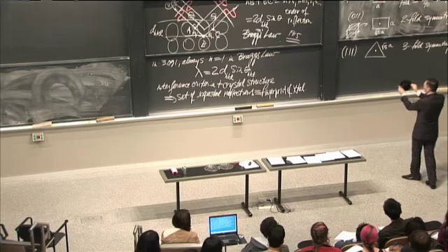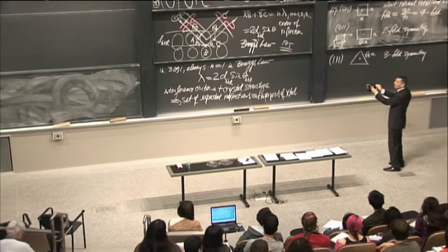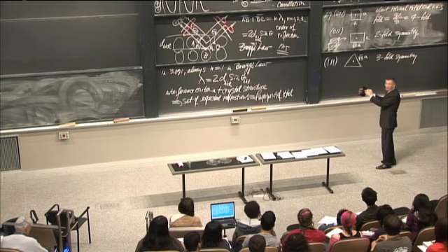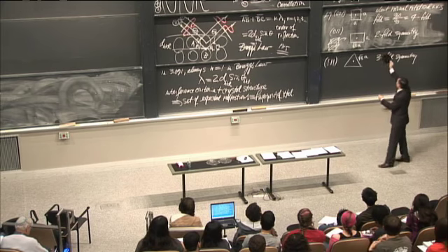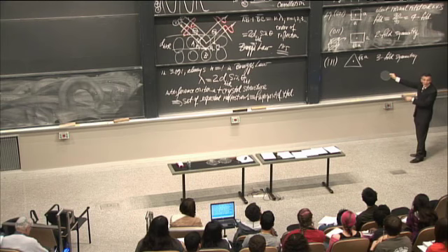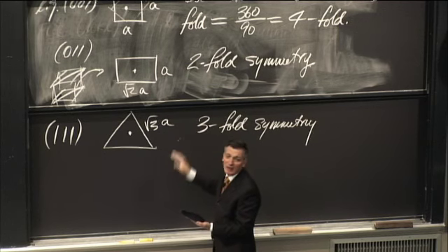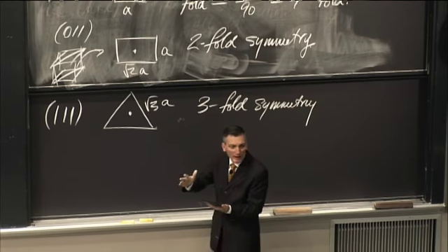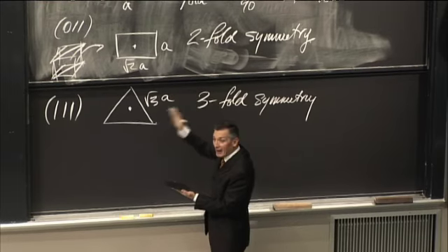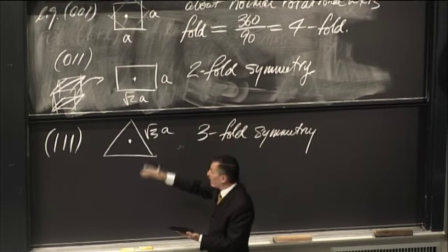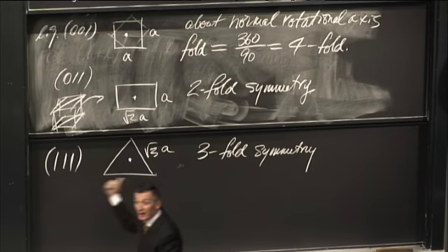So if I use the Laue technique, and put the crystal like so, bombard it with white X-rays, and look at the spot pattern, it's going to give me one of those symmetries. And if I get a threefold symmetry, I know I'm looking at 111. I mean, it's not going to be some wacko plane. It's going to be either face, edge, or diagonal. And on the basis of the symmetry in the pattern, I can tell which plane I'm looking at.